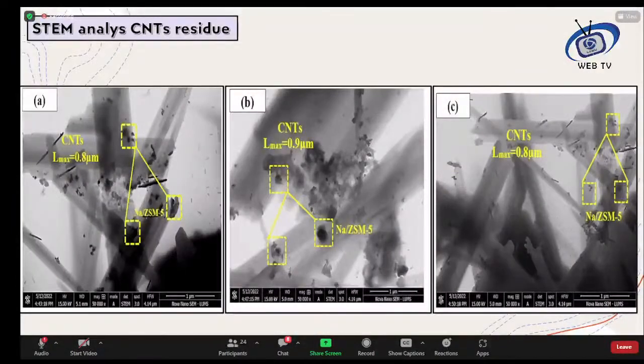Okay, then we performed the STEM analysis of the residue to check further whether these are carbon nanotubes, and if they are carbon nanotubes, whether these are single walled or multi-walled carbon nanotubes. So image A was the residue produced with the HDPE, image B was produced with PP, and image C was produced with the mixture of these two. And we can see that in these images, C shows that the tube structure is much better as compared to A and B, and the diameter is also in a controlled range. The amorphous or impurity content of the product is also low as compared to the first two images.